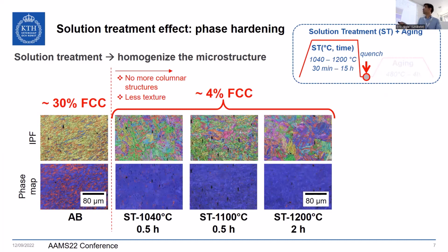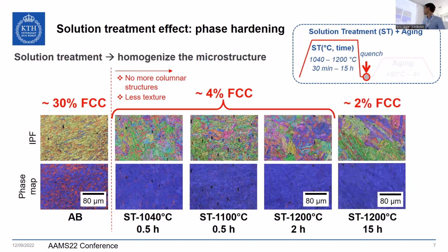So here you see that we reduce a lot the amount of FCC austenite phases. We also have much less texture, even though we keep some texture. Here is the phase mapping. And then you see we apply different solution treatments at different temperatures up to 1200 degrees C, 2 hours. For all of these, we have more or less the same 4% FCC. While for 1200 degrees C at 15 hours, so a very long solution treatment, we have a little bit reduced FCC value. So the question now is what happened during the subsequent aging.